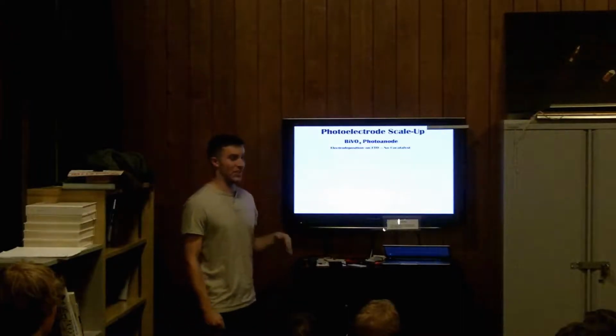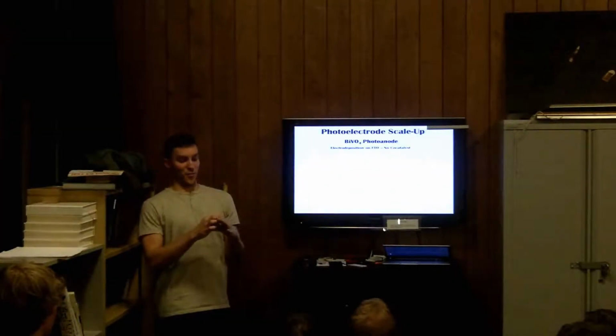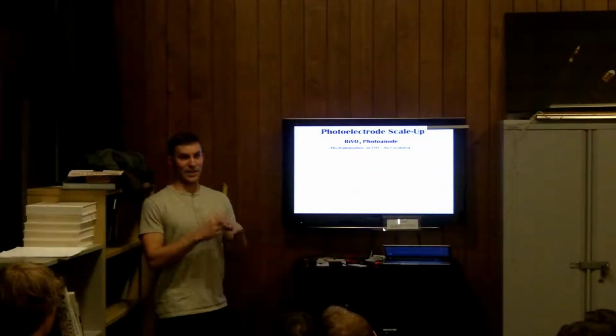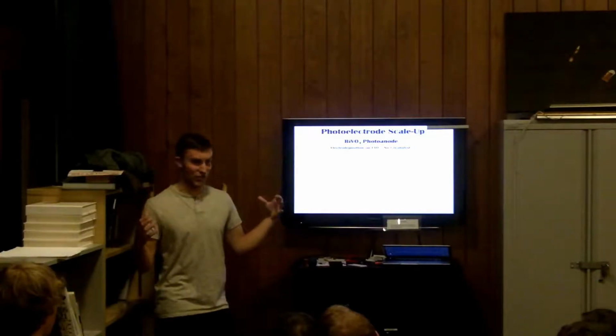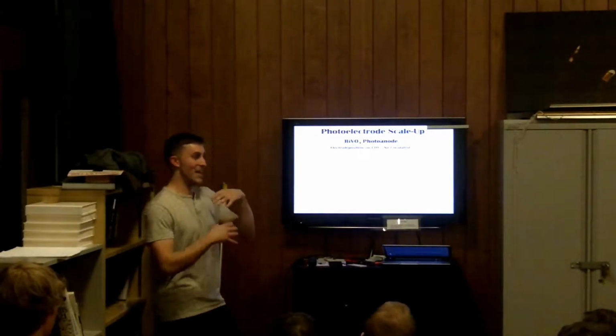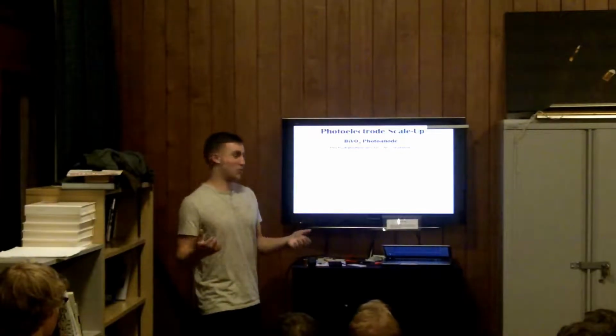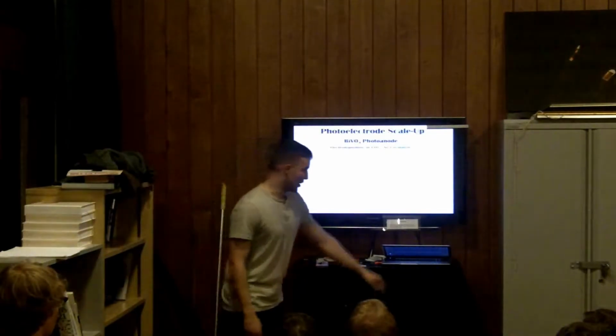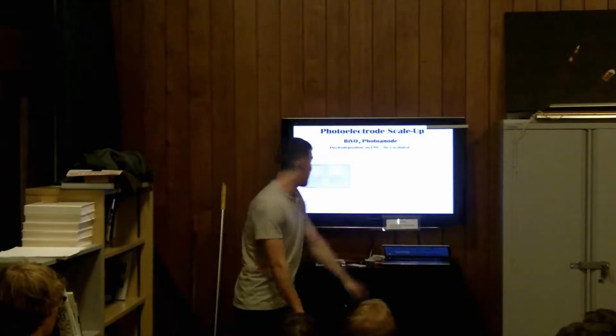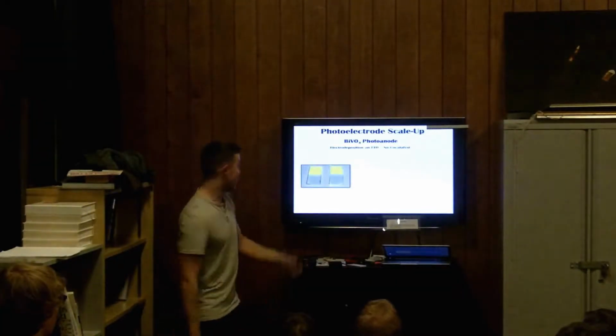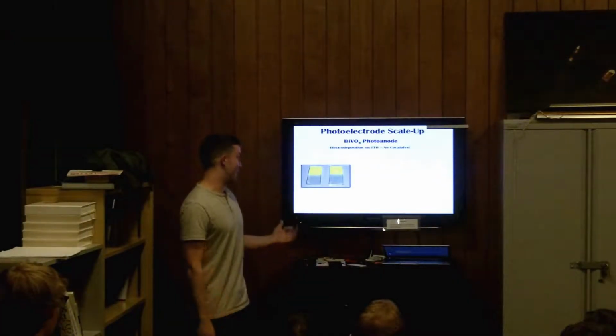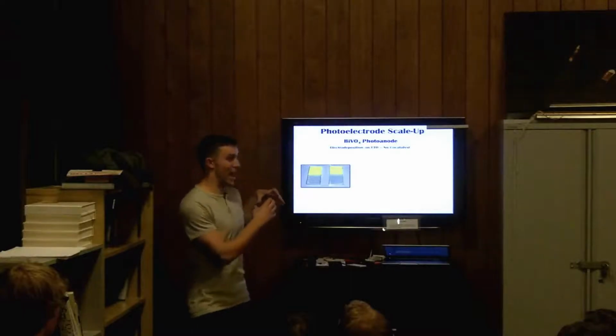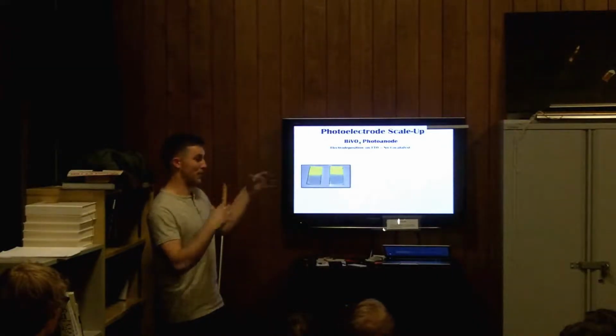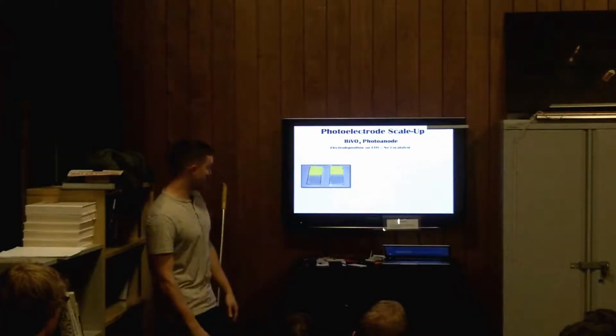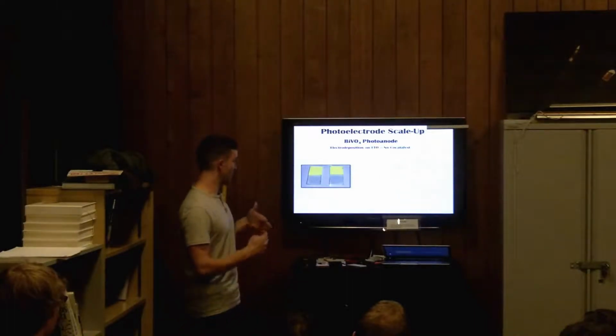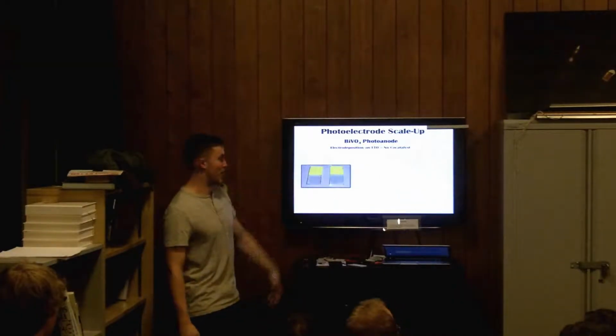I also mentioned that we're moving from this 1 square centimeter electrode scale to now a 100 square centimeter electrode scale. So that involves a lot of scaling up of the actual materials that we use. And so I'll be working with the bismuth vanadate that I showed you earlier, and these are actually slides that I've produced. This is a material that I produced following the procedure of the one that I showed you earlier. And so you can see the semiconductor there, just deposited on the FTO.